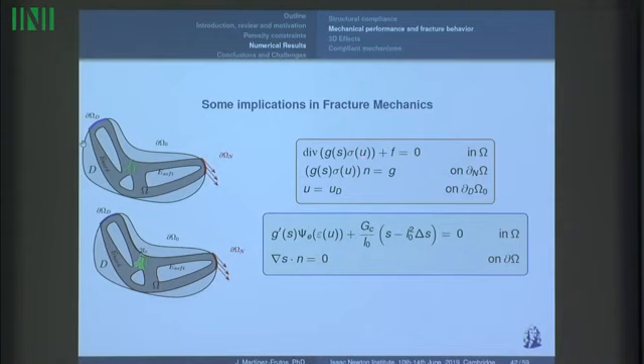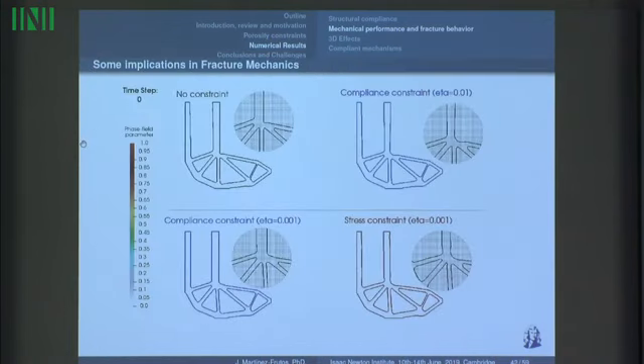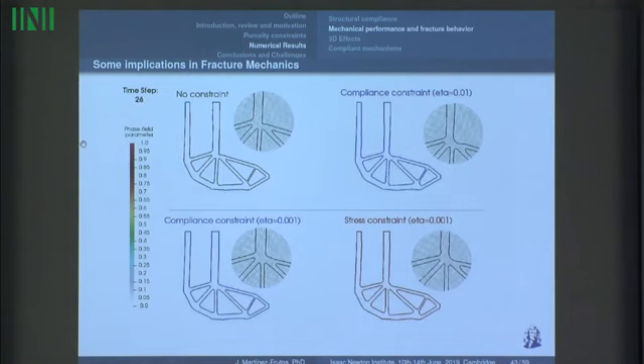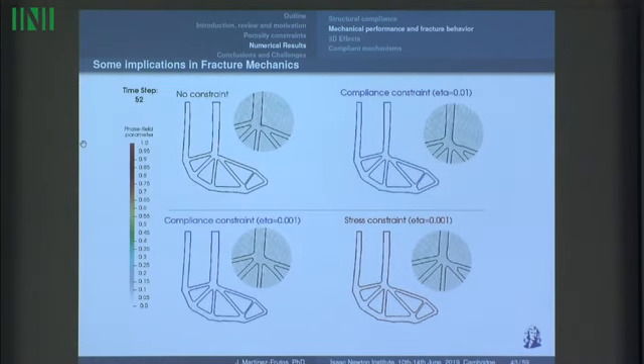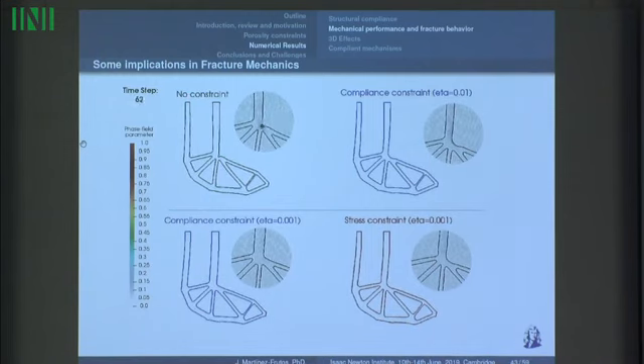The first PDE is quite similar to the elasticity system, but we have a degradation function g that applies to the stress tensor. In the second PDE, we have g prime, which is the driving force, psi E is the elastic energy, and Gc is the fracture toughness. We solve this coupled problem in a staggered way. In particular, we are going to use 100 load steps, and those are the results of this simulation. Here you can see that the first design that starts fracturing is the design with no constraint, at iteration 55 or 60 more or less.